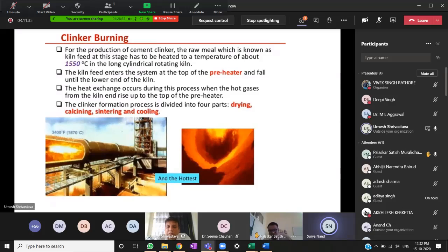That can be used, but one point of caution is the carbon content. The ash which comes from, say, NTPC or a very good power plant has a very low carbon content, while the boilers in which bagasse is burned do not have very adequate process control, and a lot of carbon particles are there. So to answer your question, if that ash has something like 2 to 3% carbon content, yes, that can be used very easily. If the carbon percentage is between 3 to 5%, then it can also be used by mixing with other ash. But if it is more than 5%, then it is difficult to use, because that will be detrimental to the cement quality. Okay, sir. Thank you, sir.